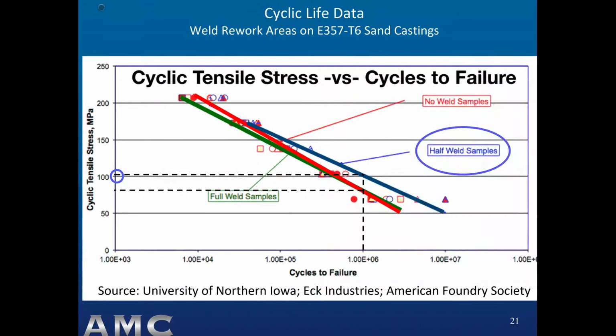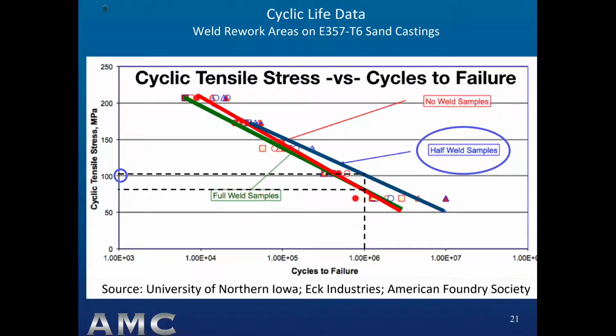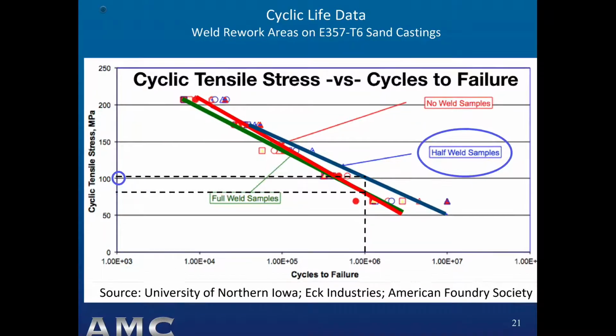Next, let's look at why that silence exists, as well as preferred ways to allow in-process weld rework in critical service casting applications. Here we see E357 T6 sand casting coupons, unwelded, welded halfway through the thickness, and welded completely through their thickness. No weld is red, half weld is blue, and full weld is green. For 1,000,000 cycles, the cyclic tensile stress to failure, the full weld was the same as the red no weld coupons, and the half weld coupons sustained about 20% higher cyclic tensile stress to failure.